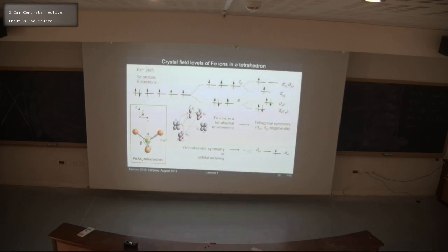One can break this degeneracy either through orbital ordering effects of these orbitals, or obviously through another lowering of symmetry in orthorhombic symmetry. And often the question is, what is the trigger? Is it electronic, or is it to do with the lattice itself suffering the distortion? This is still an open question, but I want to present today the picture coming from an electronic point of view.